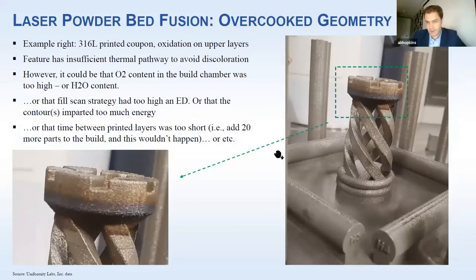So just one more example. This is something that we printed last Thursday, and I thought it looked neat. This is 316L. This part is printed intentionally to demonstrate this, but it's insufficiently supported thermally. And since 316L, I think we're at about 1500 ppm oxygen in this build, it will in fact oxidize. We're getting above 500 or 600 degrees Celsius because there are not enough pathways for the heat to leave, so you end up heating the substrate high. You'll have different amounts of residual stress at that temperature.